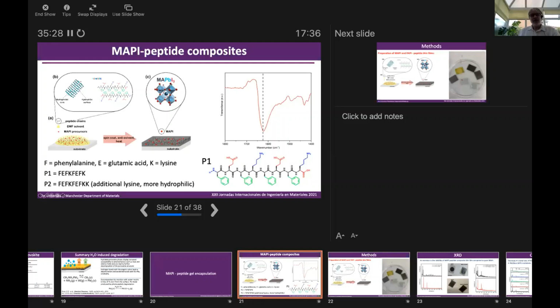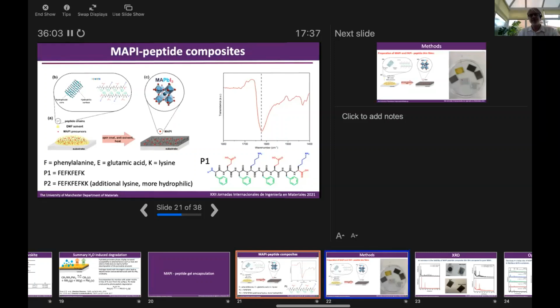So we end up with, as I say, a network gel. We swell this with a MAPI precursor in DMF. We spin coat the gel onto a substrate. We then heat it to about 100 degrees centigrade to drive off the DMF. And we know for sure that the peptide is stable below about 150 degrees C, so we end up with some perovskite. The second peptide here with the additional lysine is more hydrophilic, so we were interested to compare what happens between these two peptide gels.